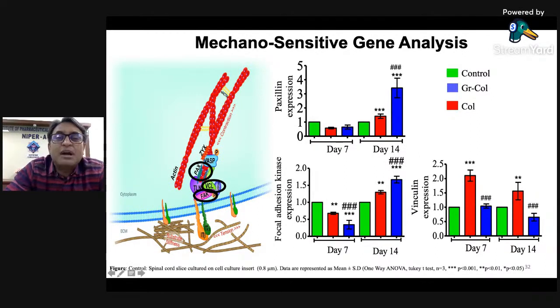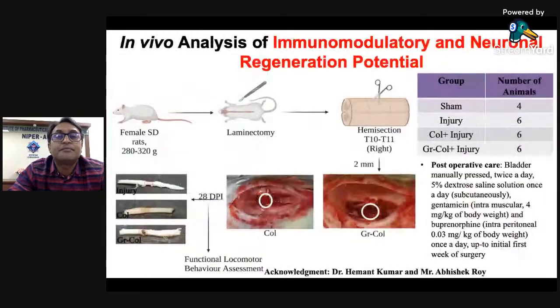For that, we chose three markers: paxillin, focal adhesion kinase, and vinculin, which are mechanosensitive genes. We surprisingly found that paxillin and focal adhesion kinase expression is very high at day 14 in Gr-Col. We could not find much difference in vinculin expression, though collagen alone showed higher vinculin. So our material is likely working through paxillin and focal adhesion kinase expression, further strengthening that our material is showing effect probably because of changes in the mechanosensitive genes.